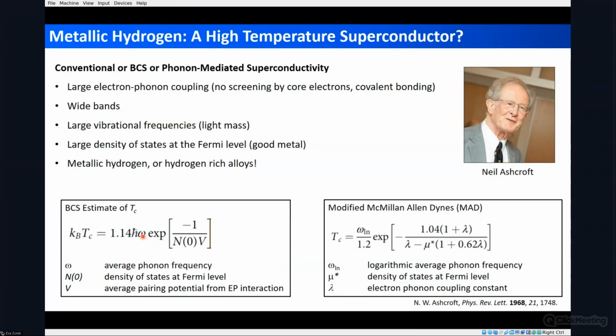So if you have light elements, it's going to enhance the TC. And here in this exponential, we have something that is related to the density of states at the Fermi level. So you want something that is a really good metal, has a high density of states at the Fermi level, and also has a large electron phonon coupling.